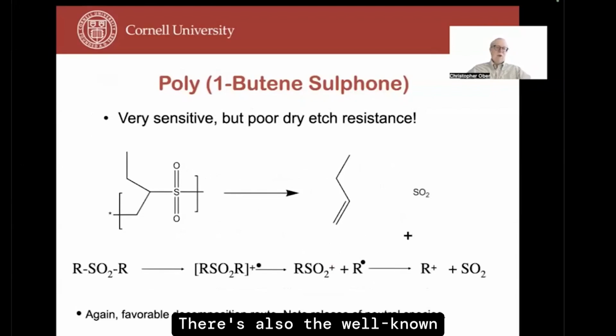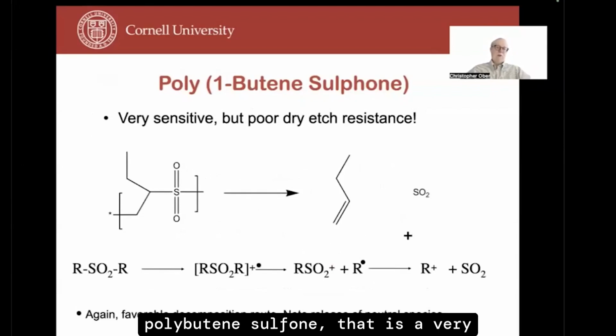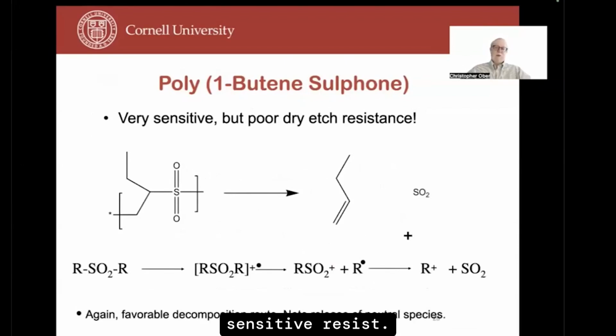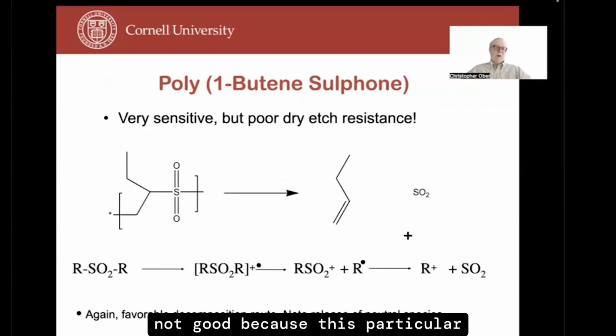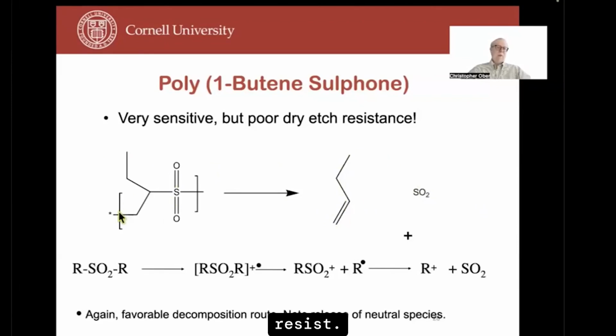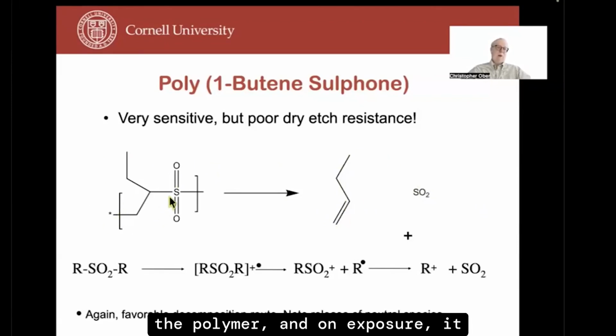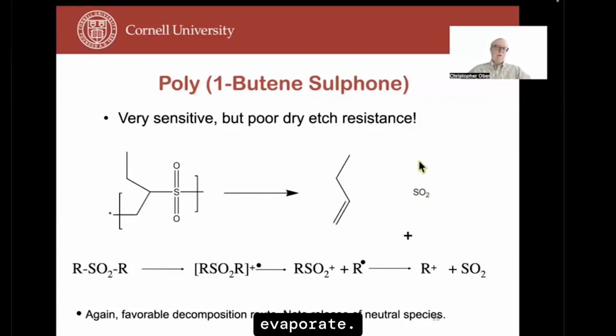There's also the well-known polyalkylene sulfone, in this case polybutene sulfone, that is a very sensitive resist, but in terms of plasma etch, it's not good because this particular polymer melts like butter when exposed to the plasma. But it's an important suggestion about how you can improve the performance of a scissionable resist. It turns out SO2 and 1-butene are the monomers of the building blocks of this type of resist. And so you can polymerize it, make the polymer, and on exposure, it reverts back to the monomers, and these components can then evaporate. So it's an all-dry development system.